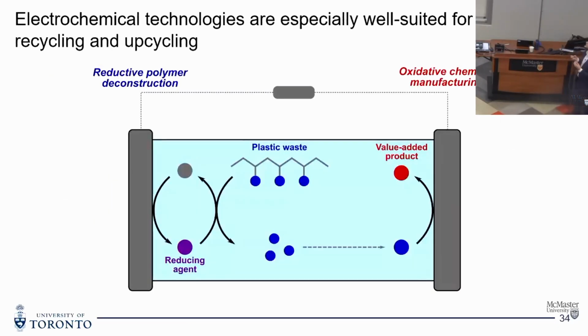And in approaching this from an electrochemical perspective, what's nice about electrochemical systems is we always have to combine an anode reaction and a cathode reaction. So if we consider one of these as a deconstructive reaction where we can generate some reagent here that will cleave parts of our polymer backbone, and then we can use our anodic reaction as a constructive reaction and build that back up into some value-added product.